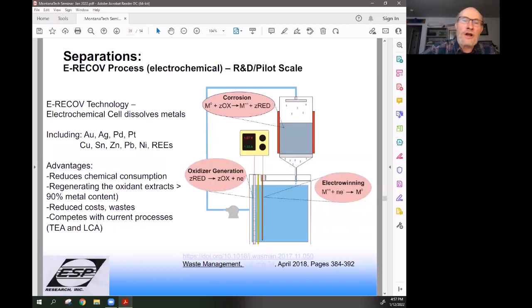The E-RECOV process is a new process that has been developed recently for dissolving metals out of electronics and or ore. Both have been demonstrated and piloted. Things like gold, silver, platinum, palladium, zinc, lead, nickel, and the rare earths. In the electrochemical cell, one has an oxidizer that they generate. So you're generating your oxidizer in situ. You're circulating that over a column of your rare earth and metal containing systems.